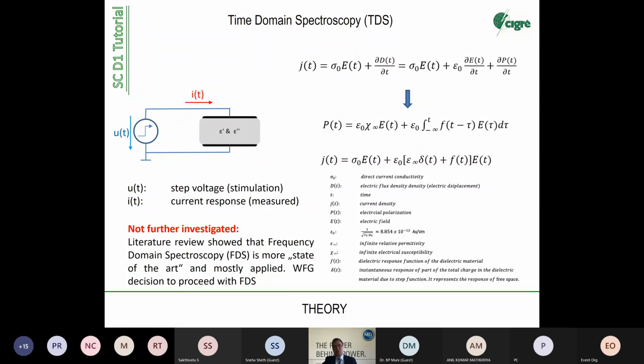And so normally what you do, here's the theory behind it. So you have a polarization contribution, you have a conductive contribution, here's the polarization, here's the conduction. So you normally use a kind of Laplace or Fourier transformation, DFT, to transform the response function into a spectrum, into a frequency spectrum, and from this frequency spectrum you can see what kind of effect is in the material. It's most probably the most effective method because it's not time consuming, it's easy to apply. What are the difficulties? Difficulties are measuring the very low currents. So the currents are in the range of nanoamperes via picoamperes and femtoamperes. So the main challenge here is to have a noise-free, distortion-free measurement of such low currents.